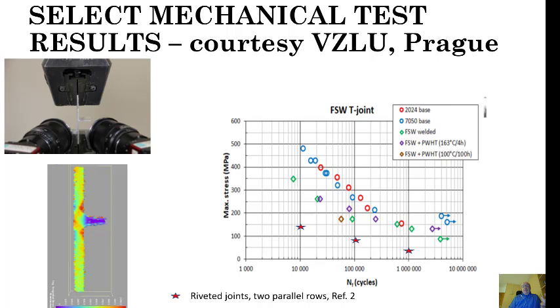Finally, we can say that we did contribute to this project by improving, even on the fatigue life of this, the way the skin is being loaded. You can see the base metal fatigue data here on top, with the weld in green showing obviously lower performance, but with post-weld heat treatment we can see some improvement, definitely better than fasteners or rivets. You can see from a different report they typically have much lower fatigue life. They fail in a different mode, but they have lower fatigue life than these friction stir welds. So very proud to say that we did contribute some to the efficiency of this project.